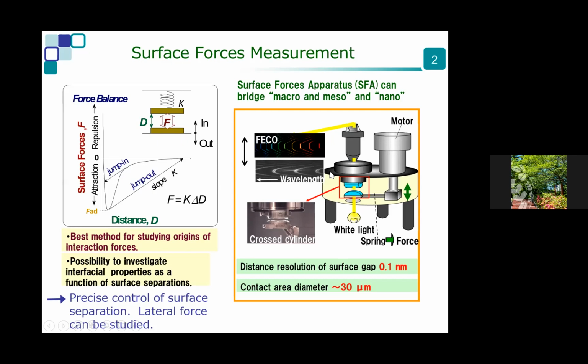The conventional SFA, surface force apparatus, is shown on the right-hand side. We have a large surface. If you only know the AFM, this is very different. We have a large spring of several centimeters, and the substrate is usually glued on a disc which has a diameter of 10 millimeters. However, the distance resolution of the surface gap is very precise, 0.1 nanometer. And the contact area is usually about 30 micrometers. So this is very large in the XY plane, but very precise in the height direction. So this is a very unique setting.